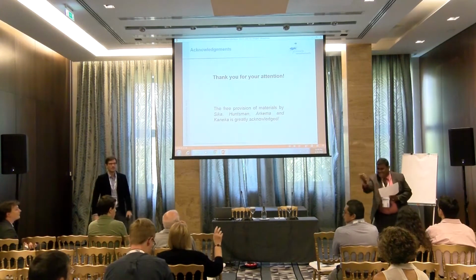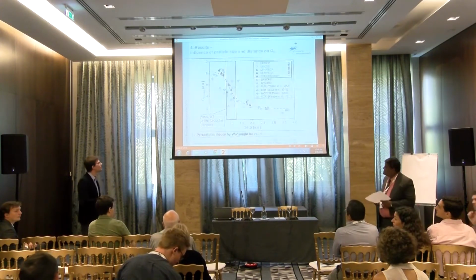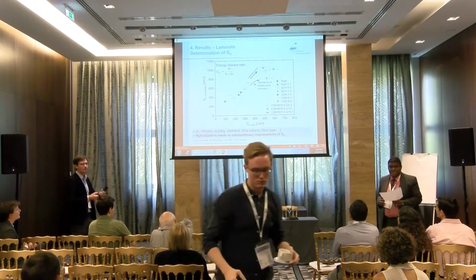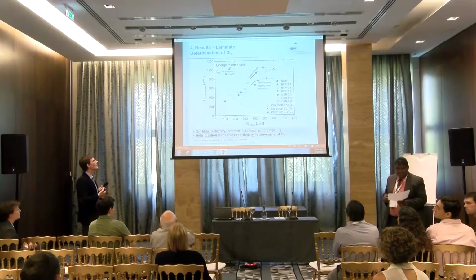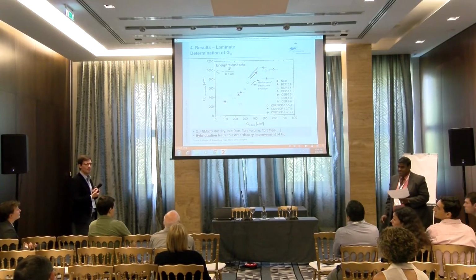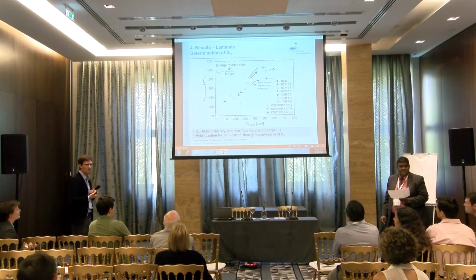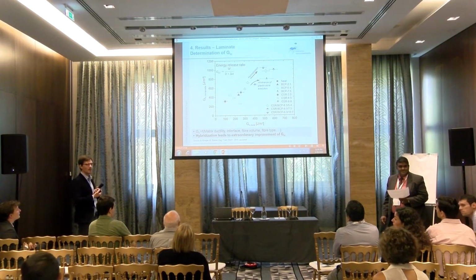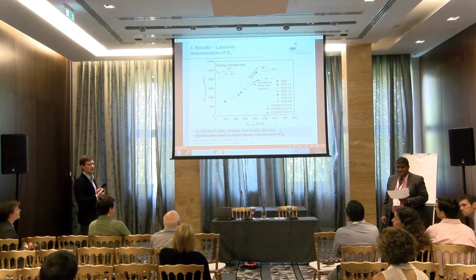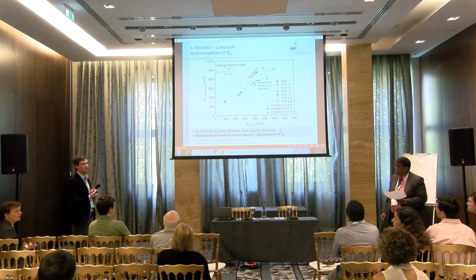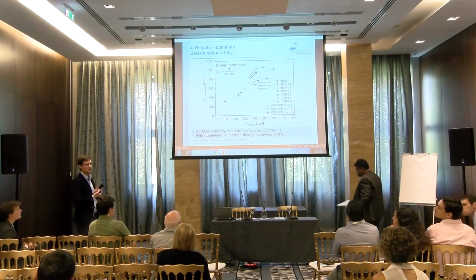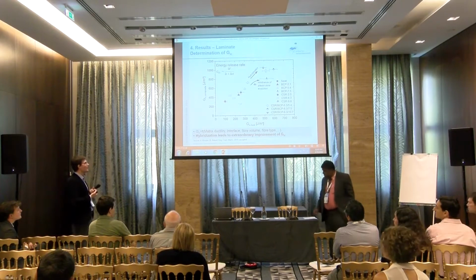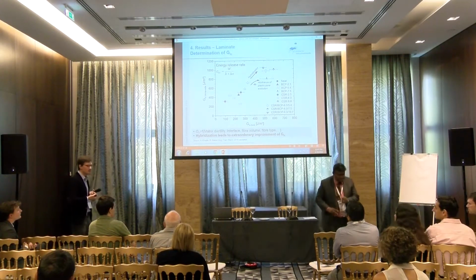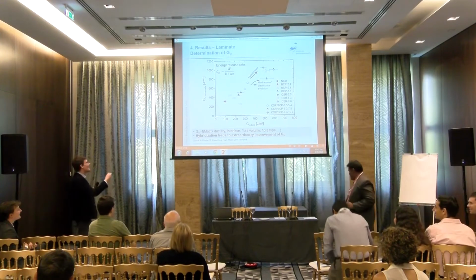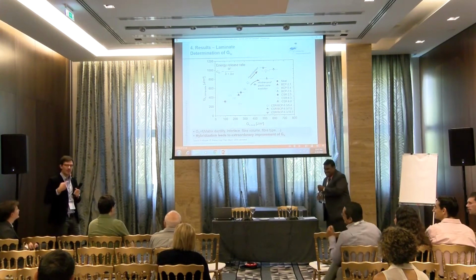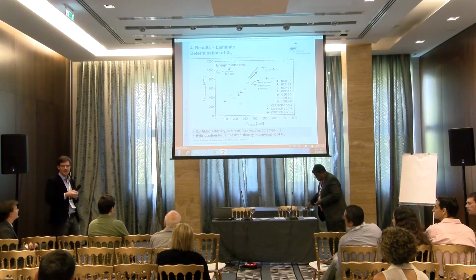Speaker, please. Can we look at slide 17, please? Okay, you show us the energy release rate, the critical one. Yes. On both axes. And you use this formula, W over B delta A. Why didn't you use the ASTM or ISO standard? I don't know. At the beginning, we simply worked with this standard, and afterwards I learned about the other standards which are available.